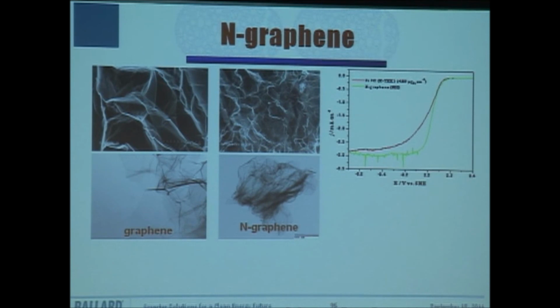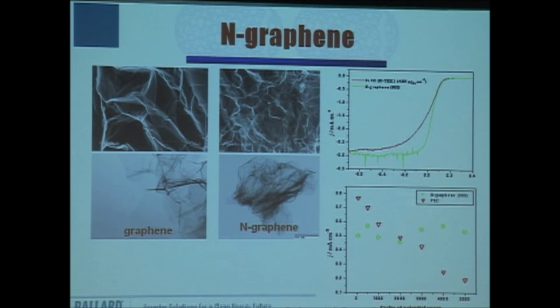Before we go into that, we actually tried using this nitrogen-doped graphene alone, without any platinum, to see if that has any benefit. This work was carried out, unfortunately, not in an acidic environment. It was in an alkaline environment. We do demonstrate even better performance compared to platinum catalyst in an alkaline fuel cell. And also interesting, under this accelerated stress test protocol that mimics real-world durability testing, we also show we have better durability.